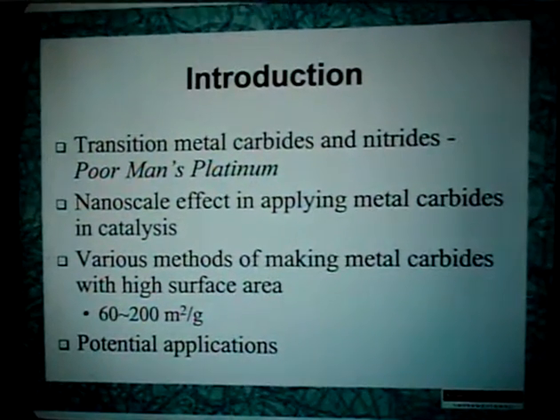So the idea of using carbides and nitrides has been around for a long time. One idea is that by putting carbon on the molybdenum and tungsten, you could modify the properties and make a material that has interesting properties. On those carbides and nitrides, we wanted to prepare molybdenum and tungsten on the nanoscale. There are many methods of preparing those carbides. The one we have been preparing has an area of about 60 to 200 square meters per gram. Potential applications for those reactions: we have isomerization, we tried the dehydrogenation of ethylbenzene to styrene, and right now we are on the HDS.